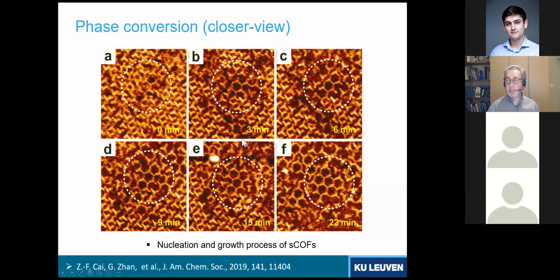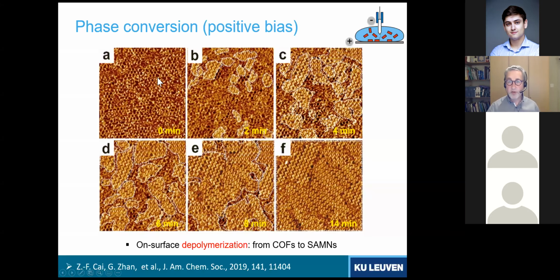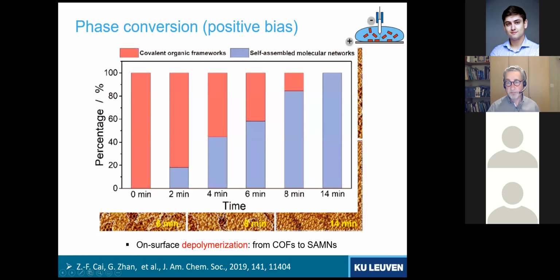Also, the opposite is possible. We can start from the covalent organic framework and induce a depolymerization reaction simply by reversing the bias. Instead of having a negative sample bias, if we go to positive sample bias, we go from the 2D covalent organic framework over here to the self-assembled molecular network over there. So we have control on the polymerization as well as on the depolymerization.